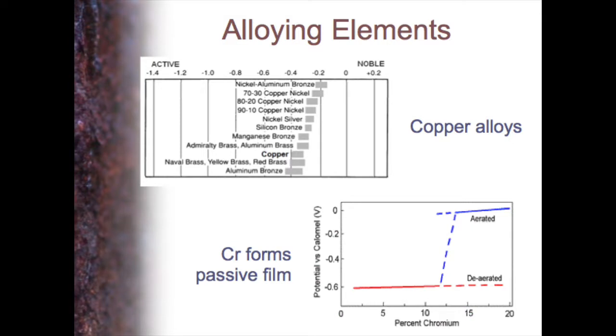If you take the galvanic potential, compare it to the EMF (electromotive force) potential, convert that to the saturated calomel electrode and find the difference between them — if you get a very noble shift, then you're getting a passive film. The passive film par excellence is on titanium, giving about a two-volt difference. With chromium alloys we're getting about a volt difference, and with aluminium also about a volt. Interestingly, magnesium and beryllium also form passive films, but they're so active to begin with that you don't get much improvement in the real world — they still act as anodes.